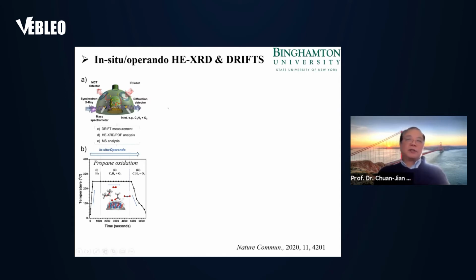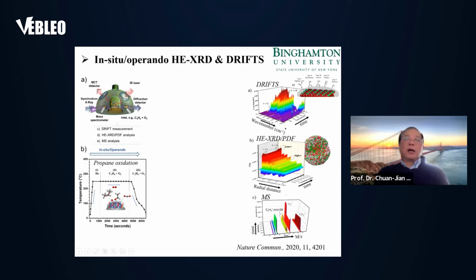For this propane oxidation, I want to illustrate that we can collect these data. We can collect DRIFTS data, which is infrared spectroscopy. We look at the reaction surface species. In the middle is the high energy XRD. We can do pair distribution function analysis, the PDF. We can analyze the metal bond distance, ordering and disordering, and phase structure. The lower part is the mass spectrometry. We can detect the reactant and the product change.